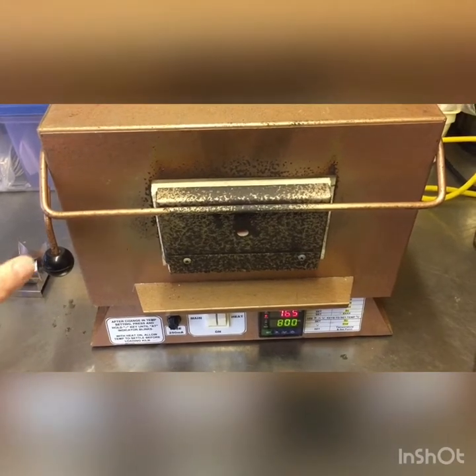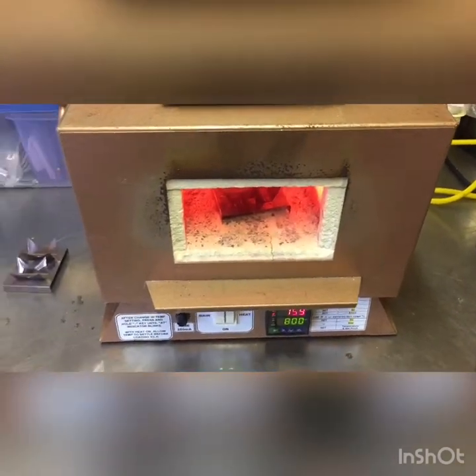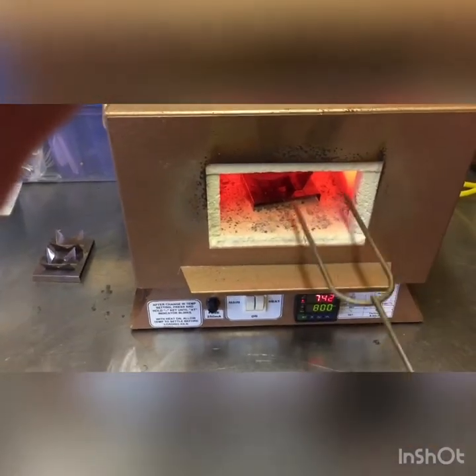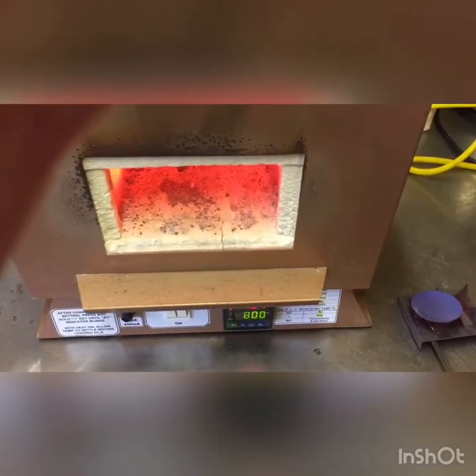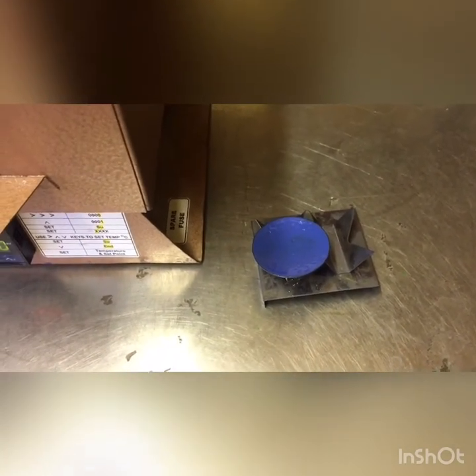My piece has been in the kiln for around 30 seconds so I'm now going to open it up and have a look and see if it looks fired. You can see how red hot the kiln is — this is roughly 800 degrees C. I'm going to get my firing fork, take my piece out and have a quick look. I'm looking to see: is it glossy? Yes. Does the surface look a little bit like orange peel? Yes — that's fine.